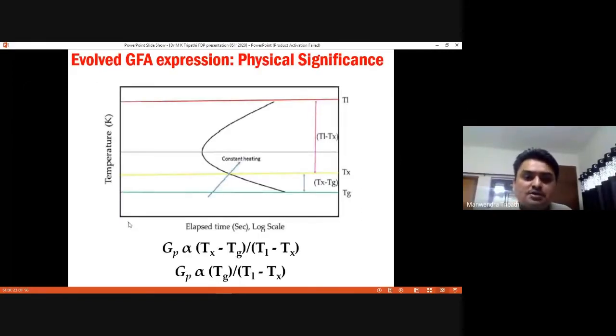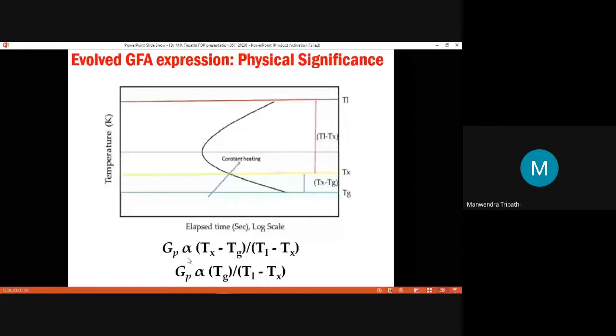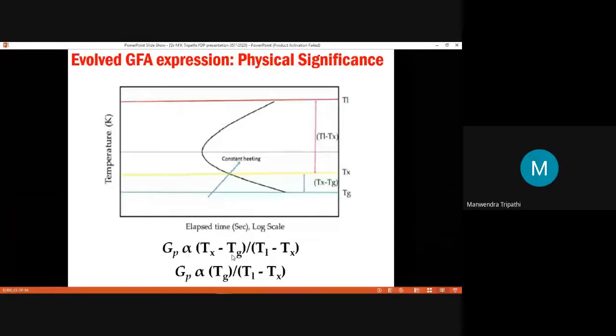First. Second thing is, what is the physical significance of this expression? For higher glass forming ability, TG should be as high as possible, so that the liquid should immediately become glass first. And second, see, this is the TG, this is TX, and this is TL. When the TG is high, glass forming ability should be high. And this region should be as low as possible, because in this region there is a high chance of crystallization. So always we find that TL minus TX is in the denominator, and TG is high, and TX minus TG, this region, so this is the physical significance, right? We are not just maximizing the correlation, but it has physical significance also.